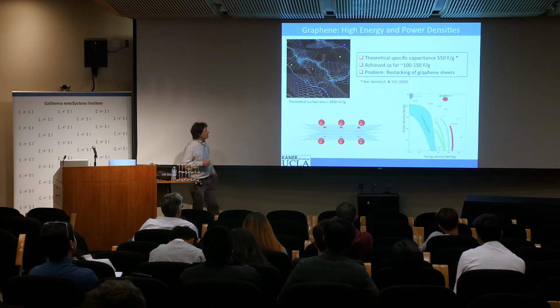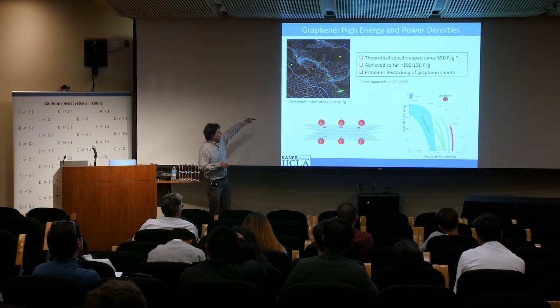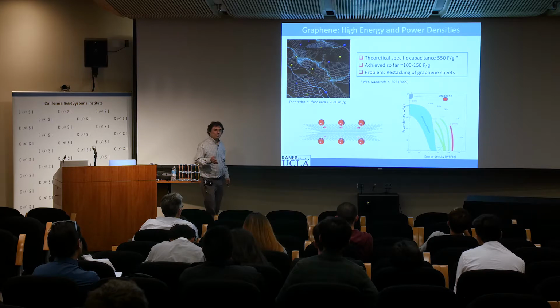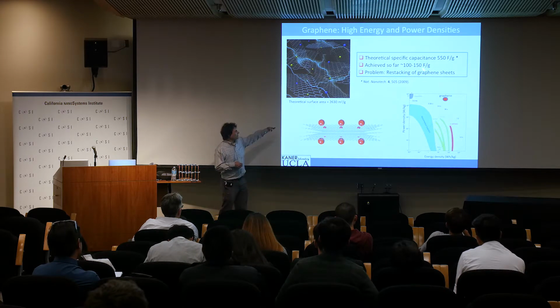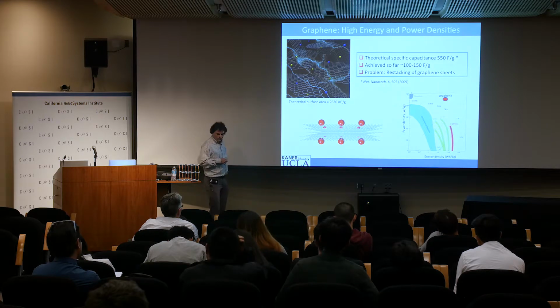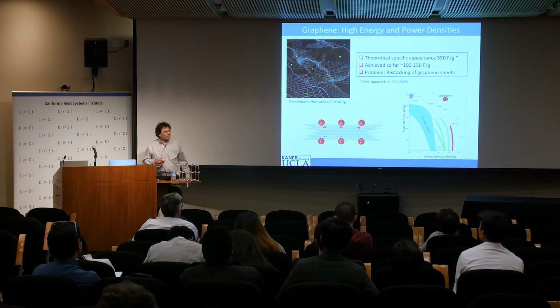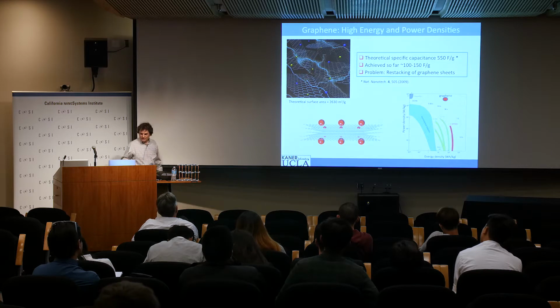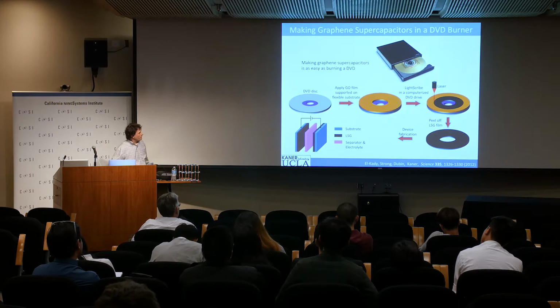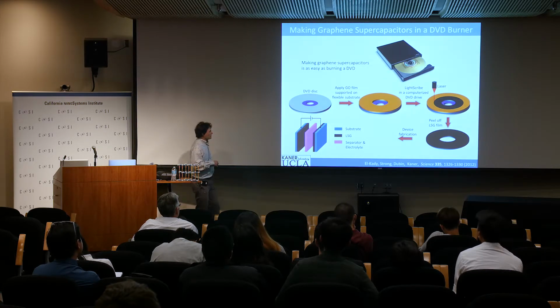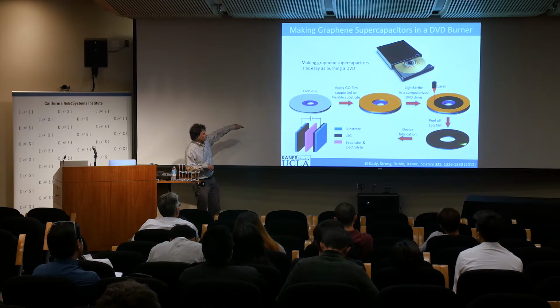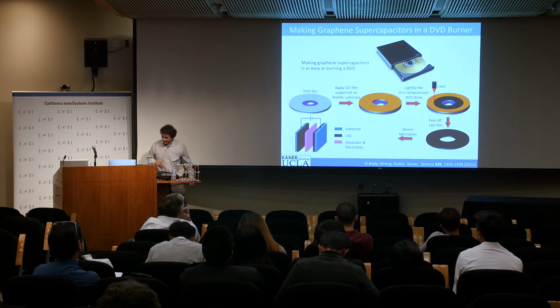However, this is based on the theoretical surface area of graphene, 2,600 meters squared per gram. And what happens is when you actually use it, in the real world, you only get about a quarter of that, of the farads per gram, the 550 farads per gram in theory. And the problem is these things restack. And if they restack, you lose surface area. But it turns out that our stuff doesn't restack. So all we did is we put a piece of plastic here, coated it with graphite oxide, told the laser to convert the whole thing. Cut a couple pieces and made a nice little cell.